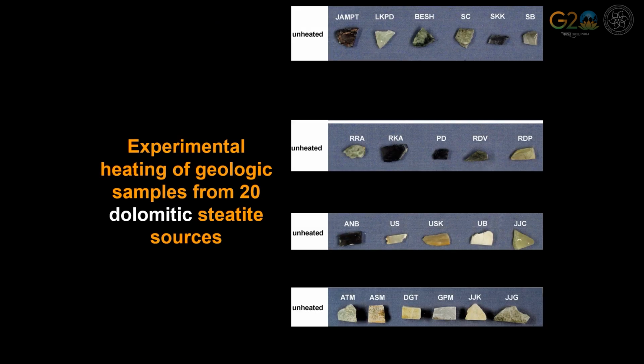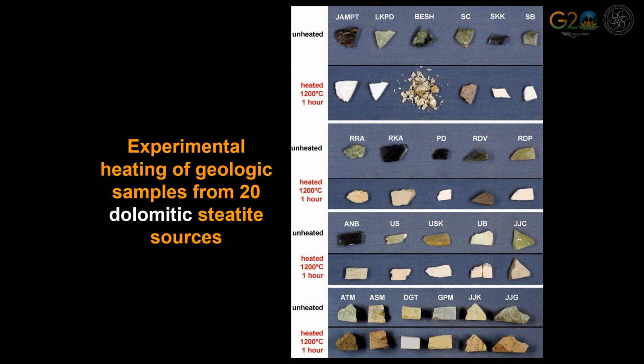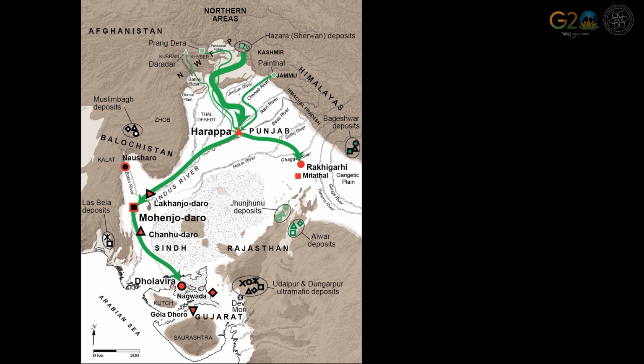So, we did another round of heating that focused just on geologic samples from dolomitic steatite sources. As you can see in the after images, even among these, not all examples became white. But, significantly, those that did were from the very same deposits in northern Pakistan and India that our provenience study indicated were the sources of raw steatite at Indus sites. So we see that white-firing dolomitic steatite came from sources to the north of Harappa.